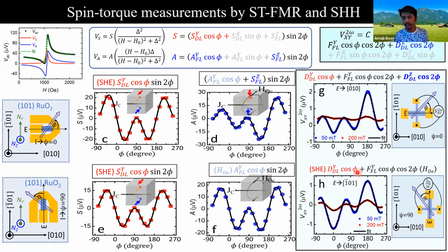For psi equal to 90, we have the standard damping like torque from the regular spin Hall effect, the cos phi angular dependence, and on top of that we have components from the Oersted field, which is cos phi, cos 2 phi. But here, on top of these two, we have this additional term that strongly suggests that we have out of plane spins generating when we run current in this crystal axis. So finally, the summary of this slide is we did two independent measurements which are in agreement, and they strongly suggest that we have very strong crystal axis dependent generation of extraordinary spin current.